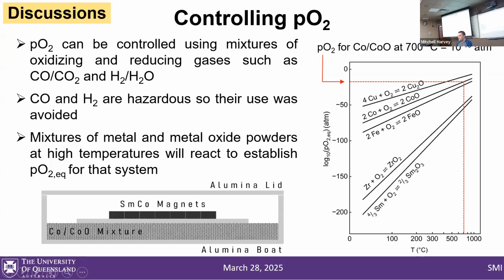What we're doing is placing the cobalt oxide mixture, then placing our magnets on top of that. The oxygen will diffuse and transport through the atmosphere and selectively oxidize our magnets. We're trying to do kinetic studies to figure out the best way to actually do this, but for right now, this is just our setup. Here are our results so far.